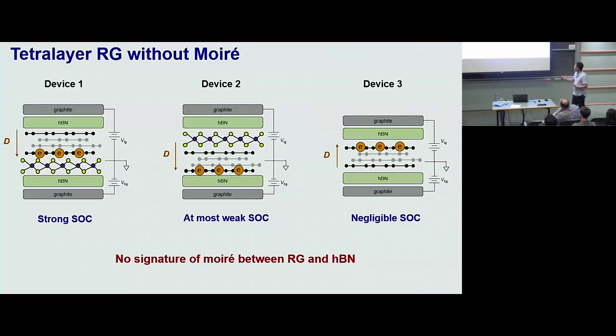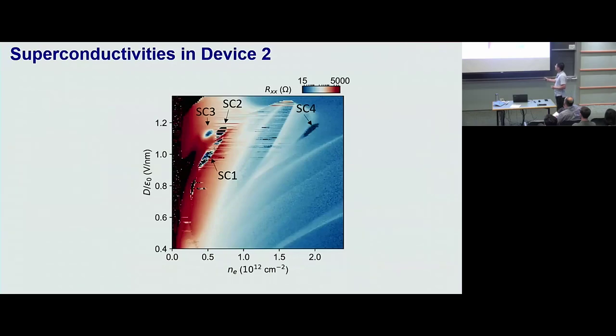Okay? So let me focus on maybe the middle one, Device 2, where there is a WSe2, but the charges in the conduction band are pushed to the layer that's away from the WSe2. By the way, there's no Moiré in all three devices, okay? This is a big phase diagram taken at the base temperature, roughly 30 to 40 millikelvin, zero magnetic field. And you can actually see that at this region, if you recall the fractional quantum anomalous Hall states, they are residing in a similar range, where there's a tilted stripe showing big resistance at low density and something at higher density. If you have Moiré, you'll get integer and fractional quantum anomalous Hall somewhere here. Well, in the absence of Moiré, you don't have that, but you do have states that touch zero in the Rxx. Okay, there's 4 of them.